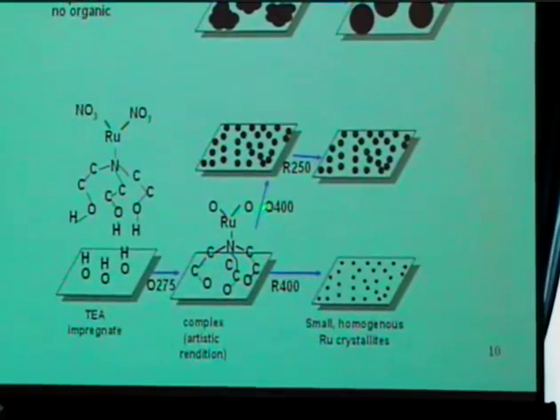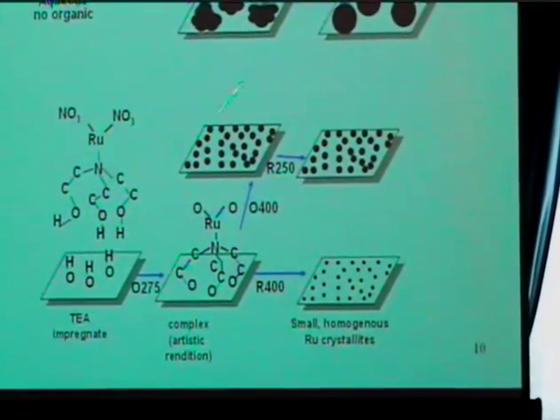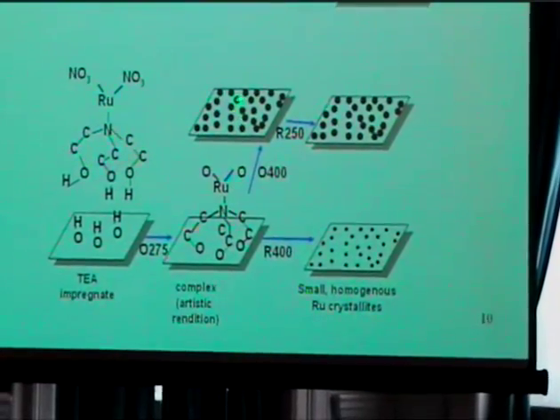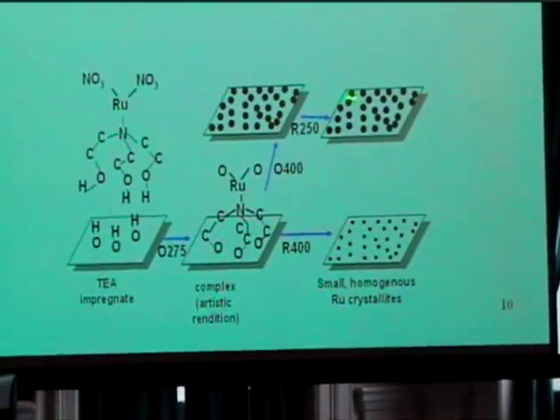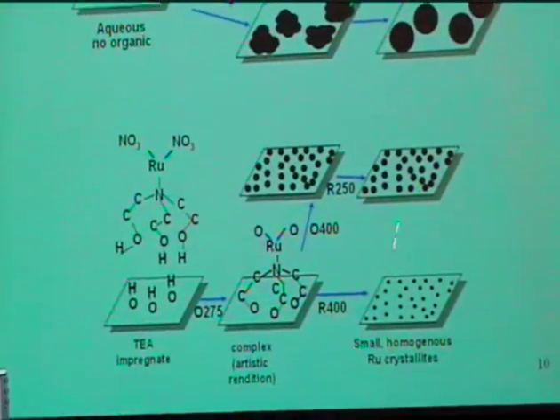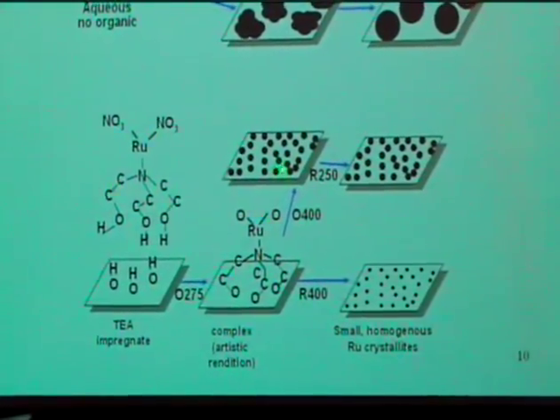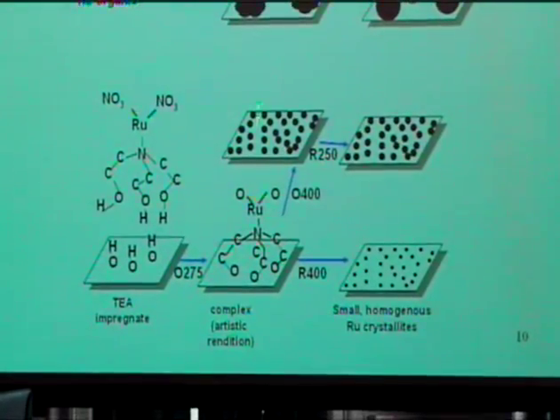If we oxidize it, well, they grow, but they're still well separated from each other. And so when you reduce these, you will get something. They're much larger than over here because you have gone through an oxide, and the oxide does have some mobility, but it's much better than what we get up here. So that's the reason why you see that.